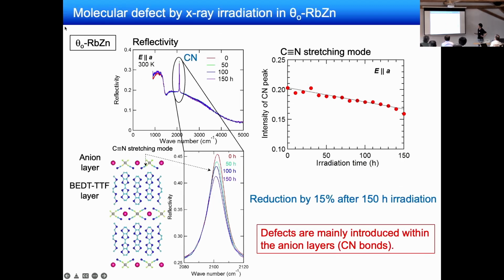Okay, so this is a result of the optical reflectivity data for the X-ray irradiated sample. As you can see, there is a very sharp peak around 2100 wavenumbers, which is attributed to the CN bonding in the anion layers. And as you can see, the intensity of the CN peak decreases almost linearly as a function of irradiation time.